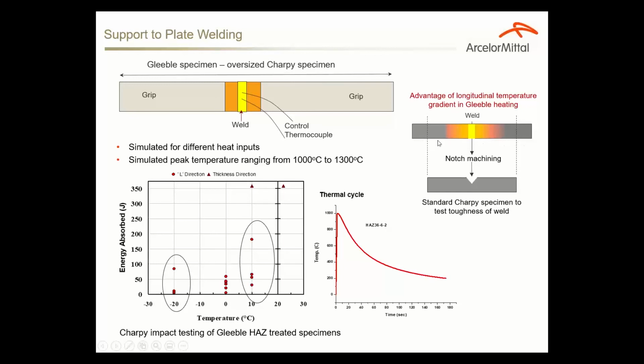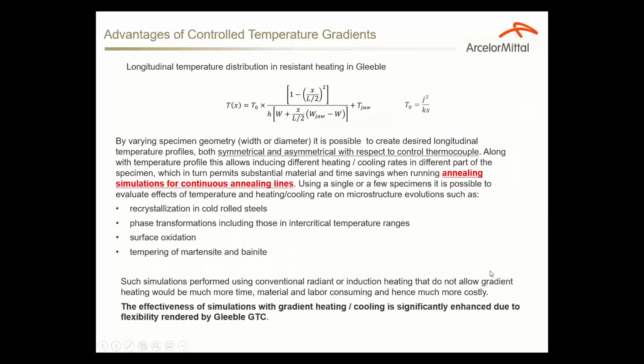We came up with this simple idea to use a full-size Charpy sample, heat treated for a given thermal cycle of welding, and then machine the notch and test it for Charpy toughness exactly at the point where the thermocouple is welded. I think that this kind of test uses the advantage, again, of the gradient heating of the sample in the Gleeble, because we're testing the toughness at exactly the weld point. We're not seeing any effect of the rest of the material on the weld toughness. So I think that's a very important advantage of the resistance heating in Gleeble.